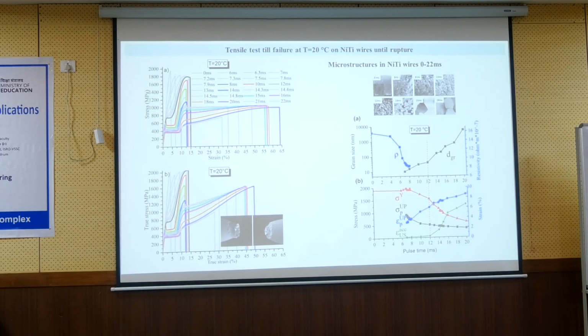The problem is that when we use, for example, the same wire in DMA, the maximum length is like 1 centimeter. If you have 1 centimeter length and you want to measure the strain precisely during thermomechanical cycling, you have to compensate all the changes of the grips. In a DMA machine you can do it. You can use a quartz sample and calibrate it. But you have to do the calibration again and again, so it is time consuming and lots of work. So we prefer to make a long wire.